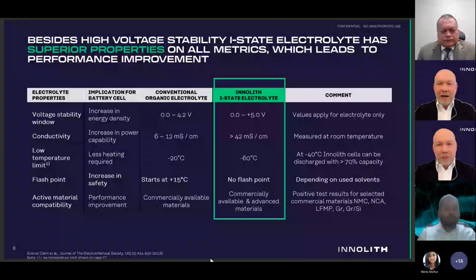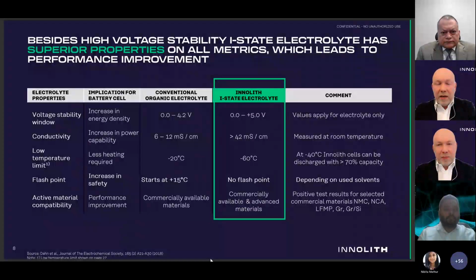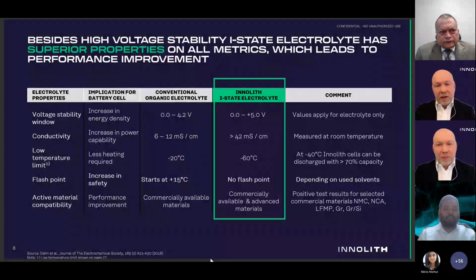Yes, our electrolyte, shown in green in the middle, compared to the conventional organic electrolyte on the left side, has, besides voltage stability, also very high conductivity. You can see on this chart that versus 6 to 12 millisiemens for conventional, we have almost 4 times more. And with this higher conductivity, we also bring power capability. There is absolutely no limitation on the side of the electrolyte for development of power capability and higher C rates in the cell.